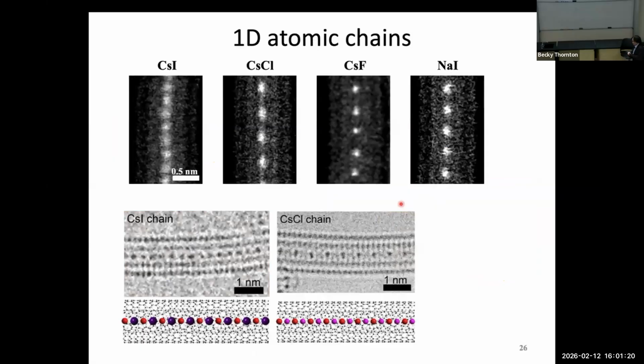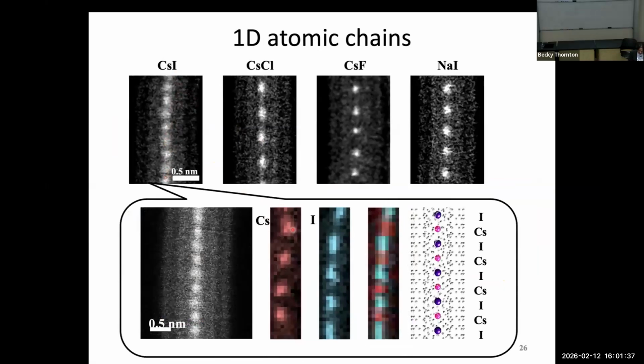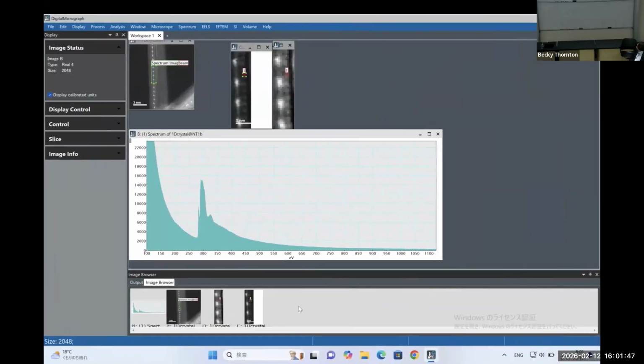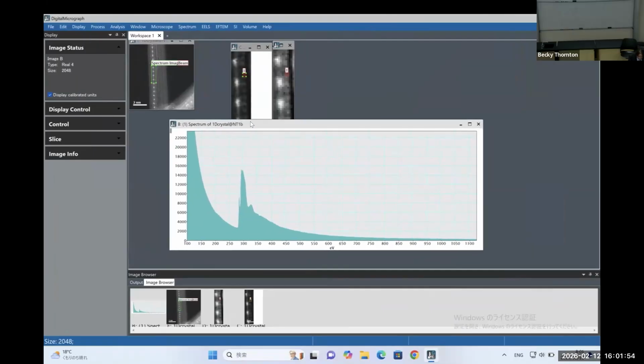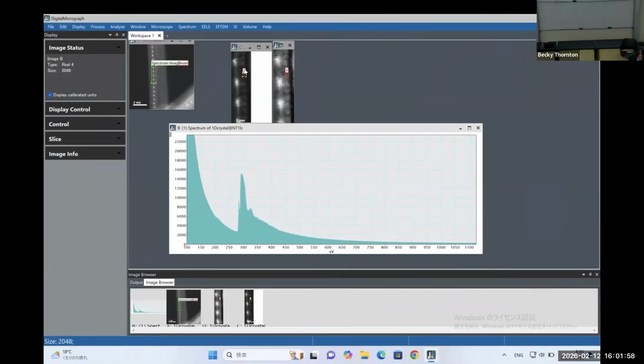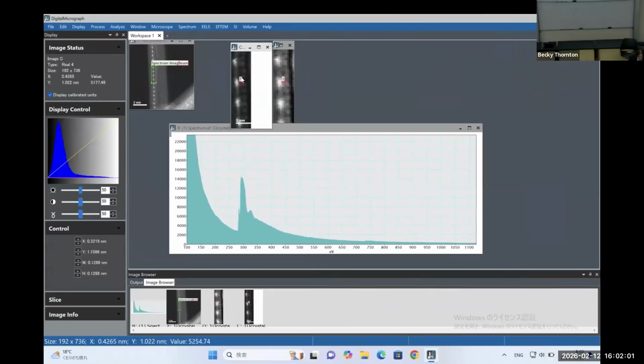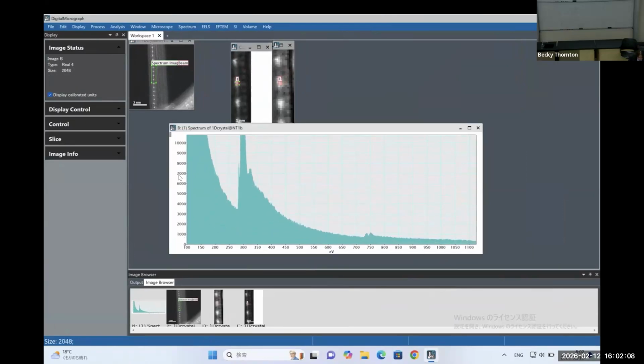First let me explain the spatial resolution. This is an example where we could get single atoms in single atomic chains in nanotubes, and you can get a chemical map, in this case of cesium and iodine. Let me explain. I will make the analysis here. If I put the beam on these bright atoms here, you can get the signal here. I hope you can see that.